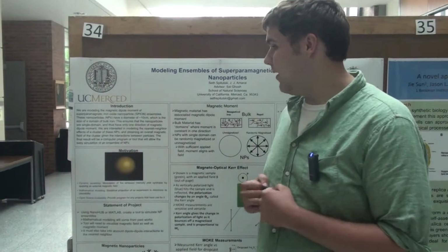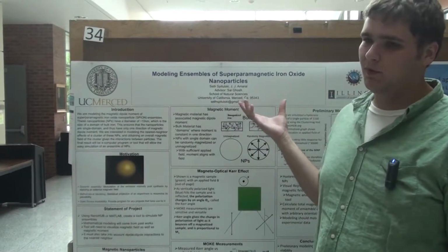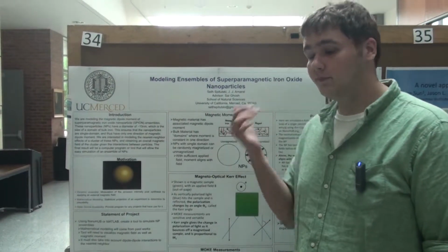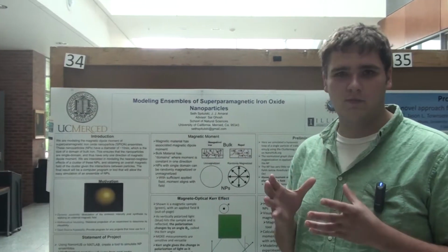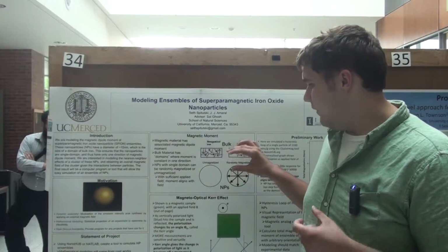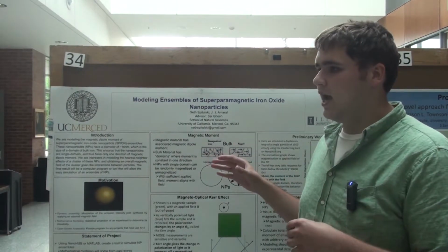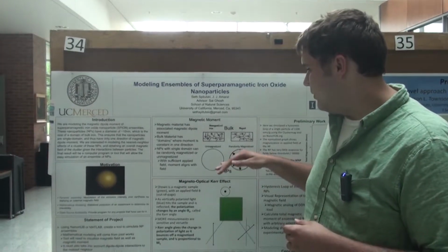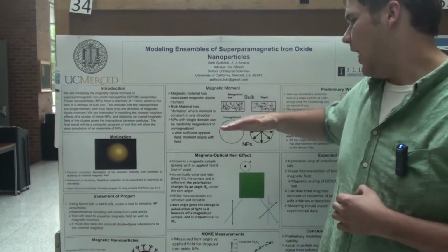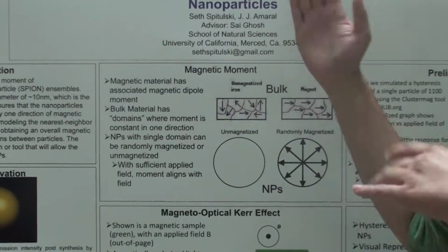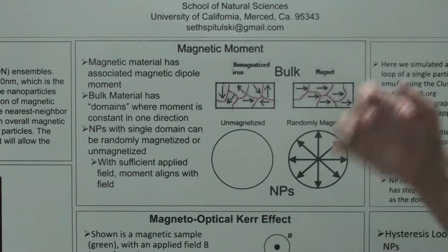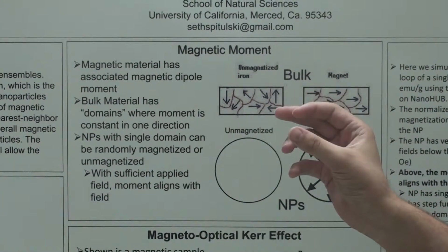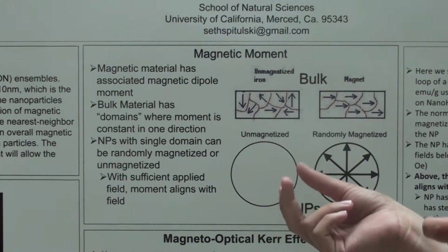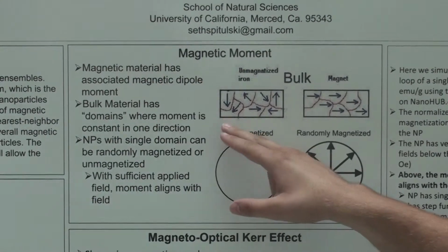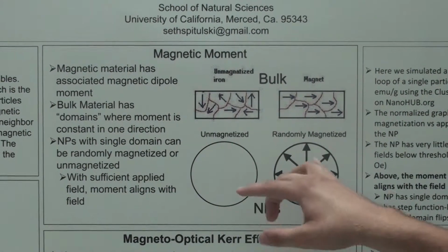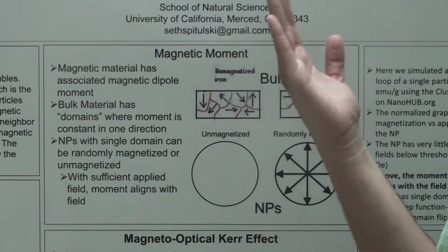I'm from UC Merced. And for my project, we were interested in modeling ensembles of superparamagnetic iron oxide nanoparticles. Now, these nanoparticles are small, around 10 nanometers. Now, bulk iron has magnetic domains, in which the total magnetic moment points in a certain direction, and you can add them like vectors. But if you have an iron oxide nanoparticle around 10 nanometers, that's the size of a single domain of bulk iron. And that means they only have a single domain, which means only a single direction of magnetic moment.